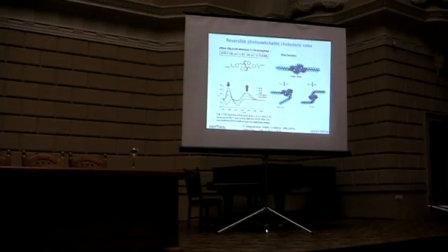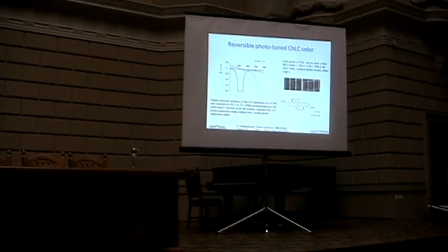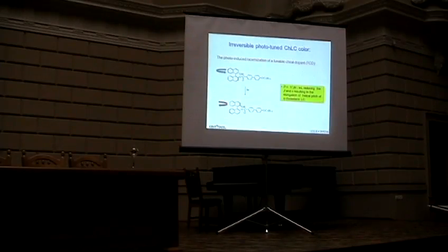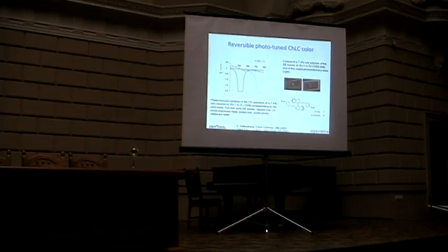Well, there is also prior work, quite a few. In 2003 there's a paper using this material. You can use the light to change the shape, and therefore your absorptions can be studied by decreasing in one area and increasing in one area. You can see that they can shift this color. That's very straightforward. But in our case, we want the color states to be reversible.